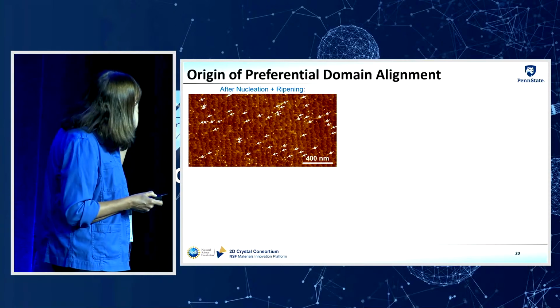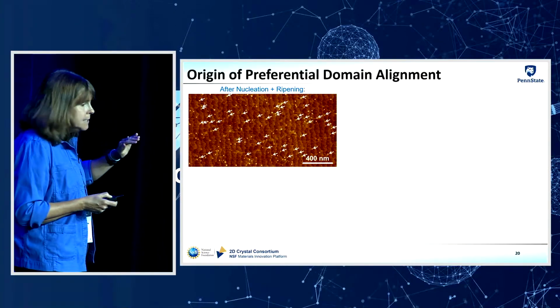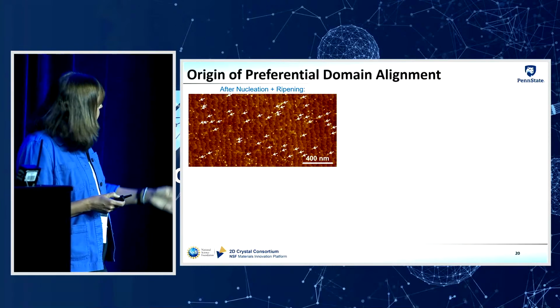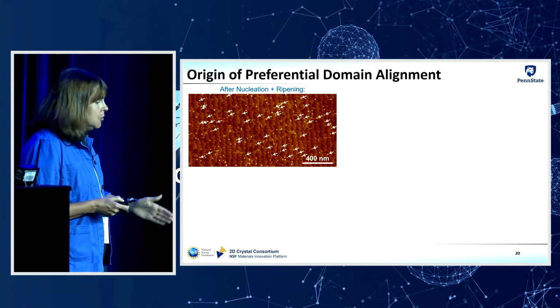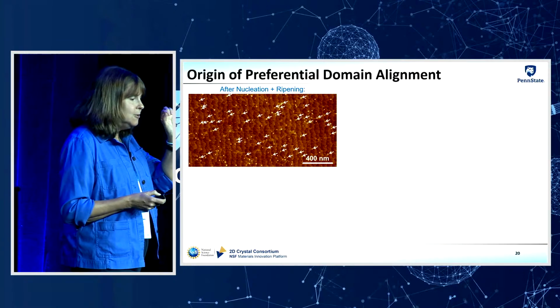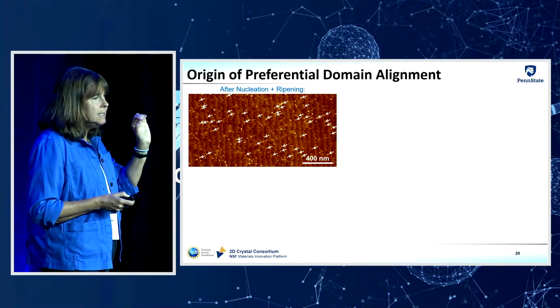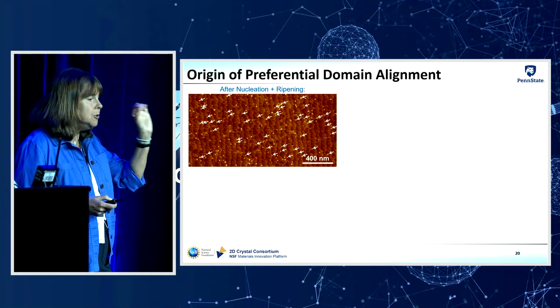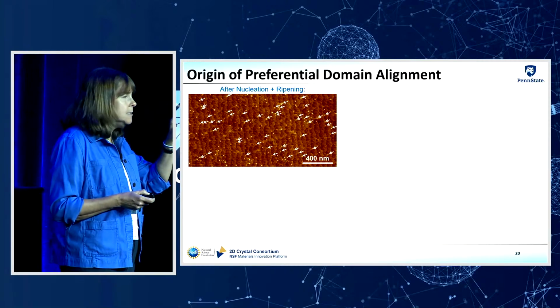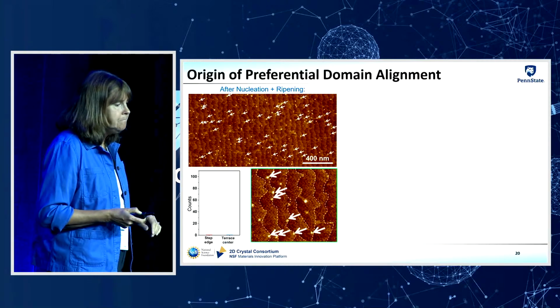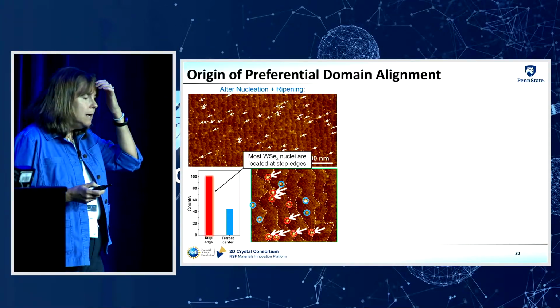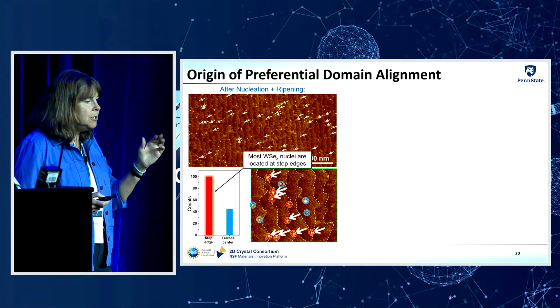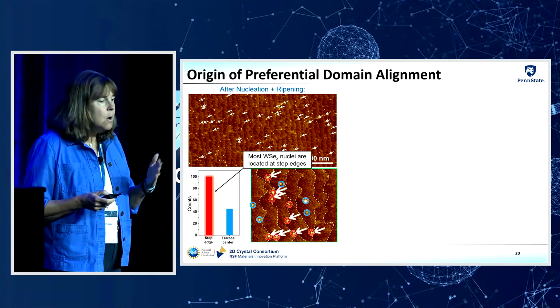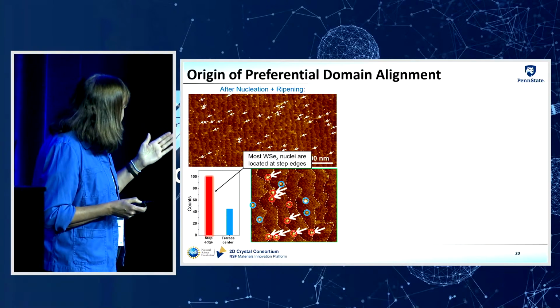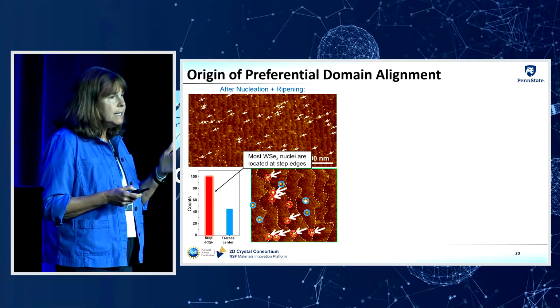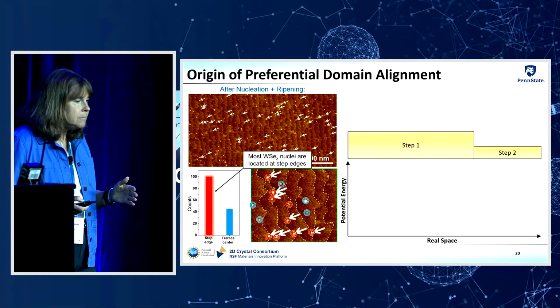So this is an AFM image of the surface. You can see the steps on the sapphire, right? They're sort of like the vertical lines. And then the tiny little dots, the white dots, those are the tungsten diselenide domains that have nucleated on the surface. And I've added some white arrows to point them out. Now, if we take a look at the location of the nucleation relative to the edge of the step, what we find is that the majority of the tungsten diselenide domains are nucleating at the step edges, right?